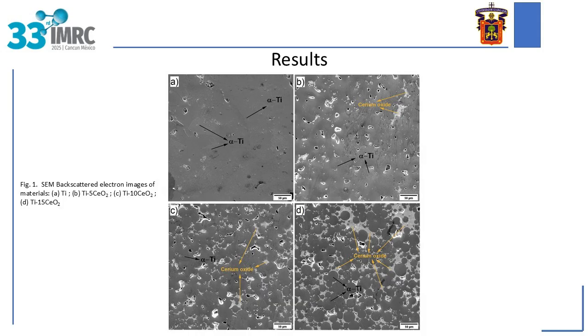The results obtained were as follows. SEM images indicate the presence of an alpha equiaxed titanium phase. As the ceria content increased, zones of lighter tonality were visualized, suggesting the presence of phases of the ceramic in the sintered materials. These phases are observed to be agglomerated in some areas, but also occupying grain and pore boundaries in the material with 5% ceria.